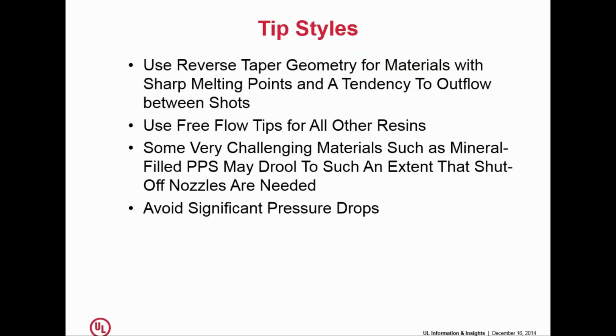Simple as that. Two kinds of tips you should be able to use. Reverse taper geometry for those materials that have sharp melting points where you need to keep the heat further back in, and free flow tips for everything else. Most of us talk about nylon tips and ABS tips or nylon tips and everything else. This is pretty much what we're talking about. Occasionally you run into a material that is so susceptible to drooling that you may just simply need a shut-off nozzle. But for the most part, you can get by with one of these two designs.